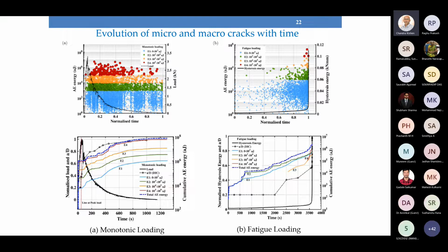Now here in this curve, we plot normalized load and a by D, that is the crack length which we obtain from digital imaging. So this black line with circles indicates the growth of crack, normalized with respect to the depth, which we have seen from the digital images. And each of these lines indicates the growth of these events with time. So here we see energy levels E1, E2, E3, and E4. And the final purple line is the total energy, the cumulative acoustic emission energy.